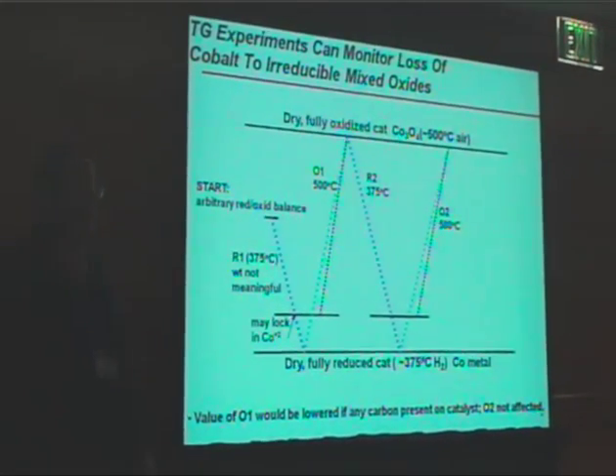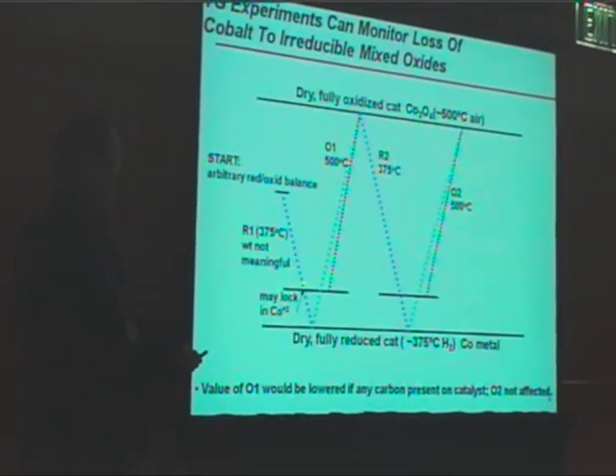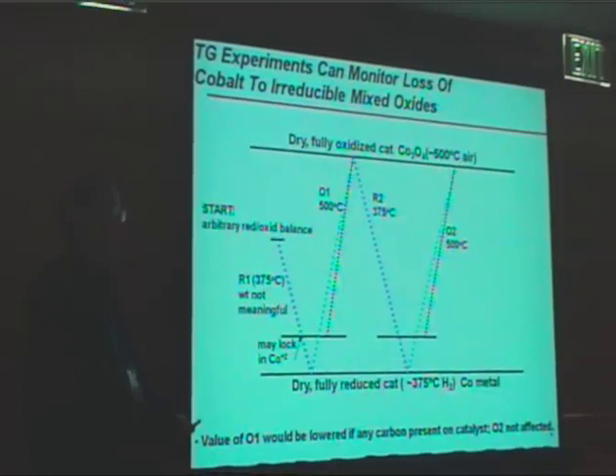And if we took that catalyst and we went ahead and retested it after 375 reduction, which we find from the subsequent oxidation doesn't have much carbon, or it doesn't have any carbon left on it, but if we just do that reduction and go back and retest it, the activity is still impacted on a deactivated catalyst. It's still very low. So in our hands and in our belief, the carbon, and I know there might be a talk later on this week, and I hate to generalize because every time I've generalized about anything in my life, it's always turned out that there's an exception. But in our hands, in the way we've been running this, we didn't see carbon being a strong deactivating evidence, and that's part of the evidence for it.